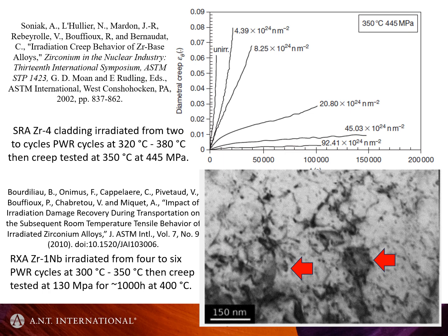And to me, I recognize it straight away. There's some C component loops in this material. And this relates to the same program as this. So one of the things I take from this is that the suppression in the thermal creep rate after irradiation that continues up to very high doses is because of C component loop formation.